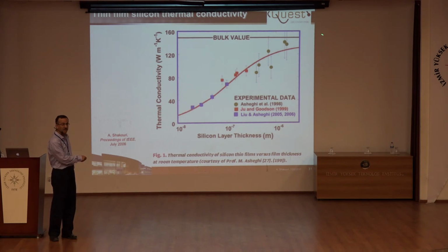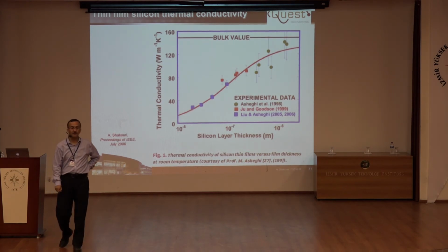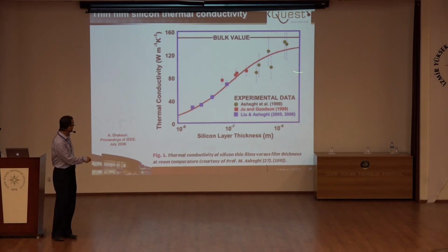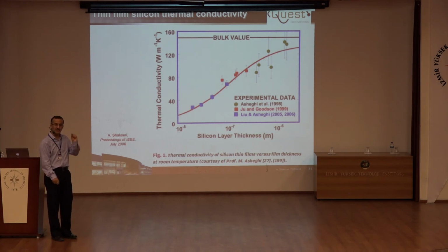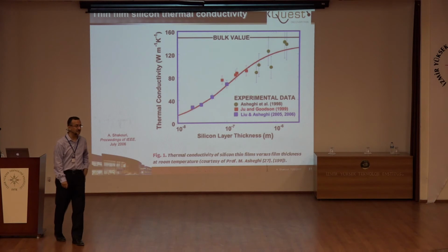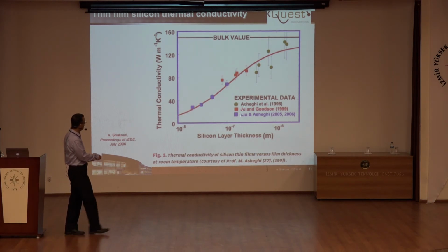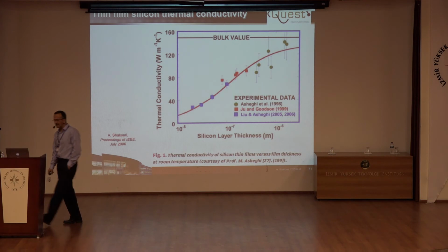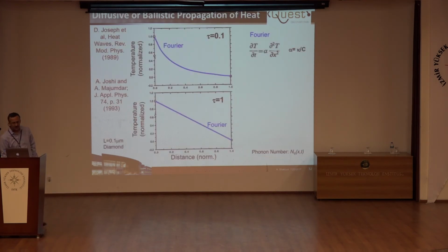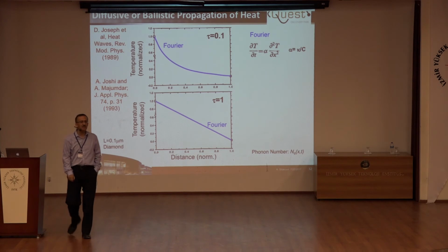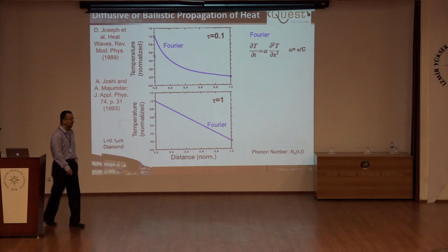People made thin film of silicon, and they realized that when the silicon is 0.1 micron, 100 nanometer, its thermal conductivity is significantly reduced, and when you go to tens of nanometer, a factor of 3 or 4 reduction. Again, this modeling says Fourier Law with an added scattering because the film is thin. Makes sense, doesn't it? It fits quite well, lots of data, lots of groups. There is not much question. But for some time, people have been worrying that there is something wrong about Fourier. What is wrong about Fourier?